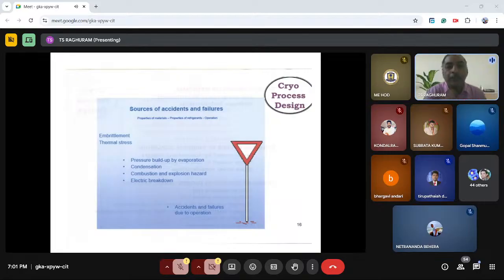Embrittlement and thermal stresses, pressure built by evaporation. Why this pressure is building up is when a cryogen is sitting in a container, ambient temperature is at 300 Kelvin, and this liquid cryogen is at 77 Kelvin. A delta T of 200 K is driving it. Suppose if you are using oxygen, nitrogen; if it is hydrogen, it is too critical. It is 20 Kelvin, so 250 Kelvin difference is there. If it is helium, it is almost 295 Kelvin delta T. This delta T is the driving thing which causes the liquid to get evaporated inside. If the insulant is not proper, because of the continuous steady state conductive, convective, and radiative heat, you will land in problem. So pressure buildup is the dangerous thing which you need to attack.